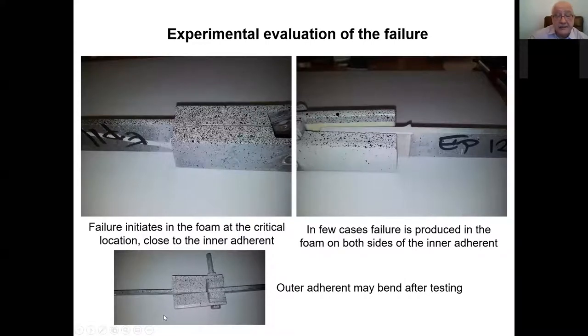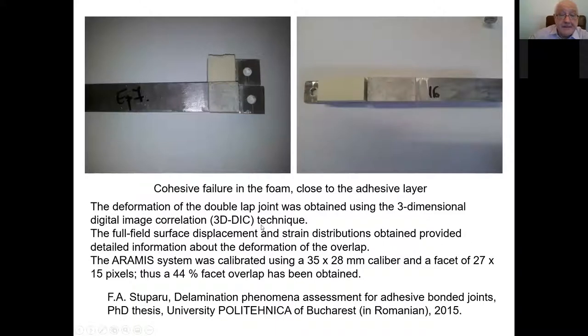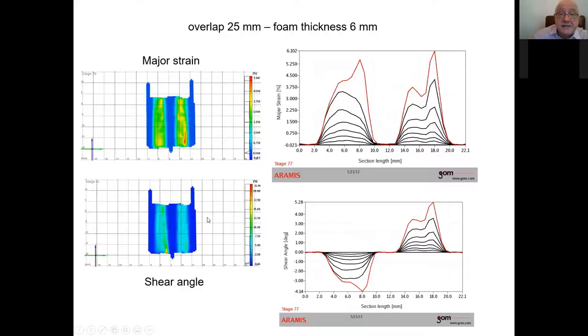You may also have some bending of the adherent. If the adherent is thinner, let's say like 4 millimeters, it may bend, or even less. And in a few cases, we had symmetry in failure at the inner adherent, in between foam and the inner adherent. So in most of the situations, we had cohesive failure in the foam close to the adhesive layer. We used a caliber of 35 times 28 millimeters, a facet of 27 by 15 pixels to have more precision in measurement. We sent it with a PhD thesis some time ago.